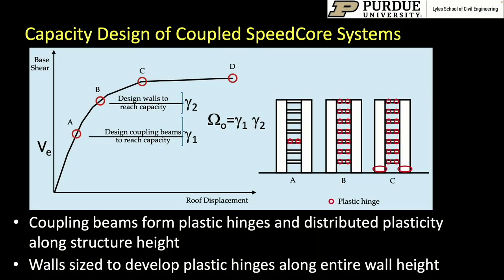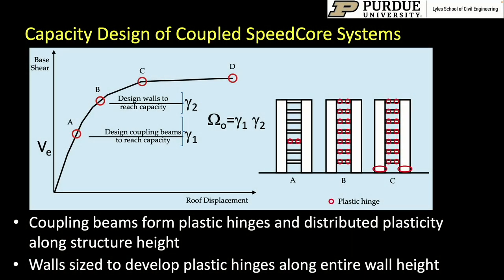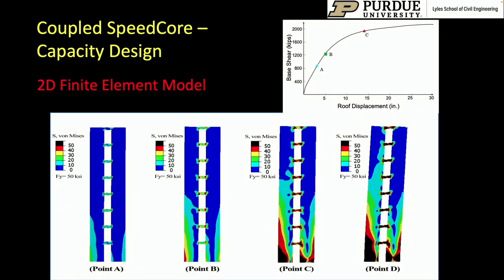Eventually, if you keep pushing on the system, you reach point C, where you form plastic hinges at the base of the walls. And by the time you get to point D, you start getting fracture in the coupling beams and eventually fracture in the walls. So this was done to distribute the plasticity along the height of the structure. And we want to distribute the plasticity along the height of the structure because doing that gives me a more ductile system, which will allow me to reach an R factor of 8 rather than 6.5, which is being used for the uncoupled system. We implemented this capacity design principle in order to design several archetype structures.